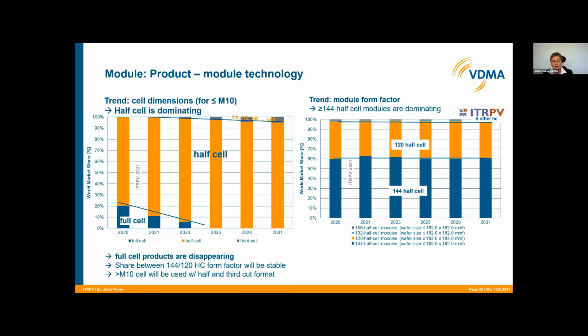Now, how many cells are cut in half, and how many are still used in full? You see here, this year it's only about 10% full cells and nearly 90% half cells. Only the wafers bigger than M10 may be cut mostly into third cells. And the form factor, so how many half cells a module has: we see clearly that the bigger ones, the 144 half-cell module types, are about 2/3 or 60% of the market. And the other 40 or 35% are the smaller ones. This fits the market split between rooftop applications and power plant applications.